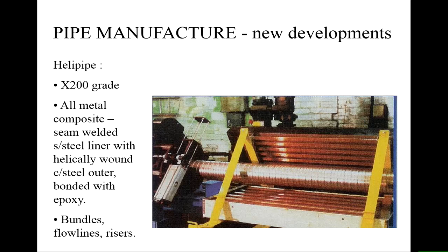The key thing with risers is they're not used for ones where there's big wave heights. If it's just a fixed position riser with a small movement on the surface, they have quite long lives. If you've got a big fatigue component, you probably wouldn't use these systems. And the problem is not so much the epoxy side, it's the liner has to cope with all the movements, and you'll breach the liner before you fail the outsides.